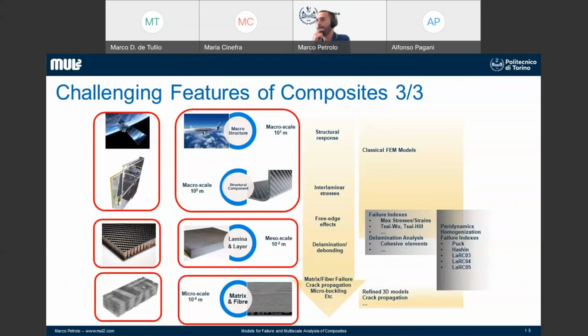And as I said, the other issue is that composites are multiscale. This means that if you want accurate results, sometimes you need to take into account more scales. Usually we can have at least 3 different scales. We have the structural or macro scale. Then we have the mesoscale, in which we consider each lamina. And then we have the microscale, in which we model each fiber and matrix. So depending on what you are interested in, you have to deal with one or more scales.